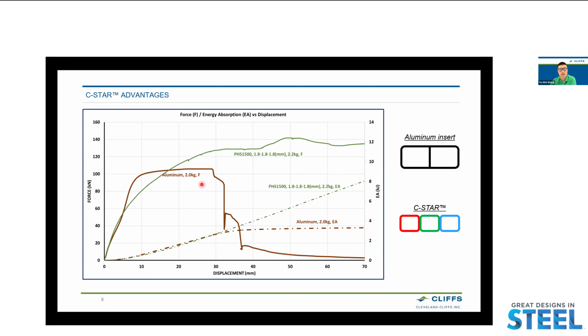So first, let's take a look at the force. From 0 to 17 millimeter, the two force lines are very close to each other. And after 17 millimeter, steel starts to outperform aluminum. Value-wise, the C-STAR peak force stays at 143 kilonewton at 50 millimeter. And for the aluminum, it's 107 kilonewton at 17 millimeter. So we are 30% more than the aluminum on the peak force.